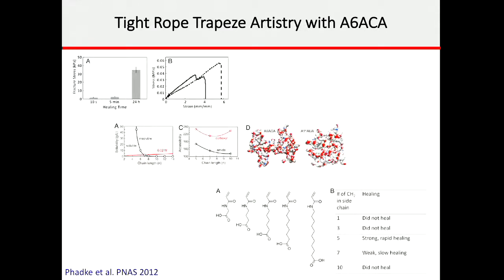Okay? Now, this paper also told us that if you have too long a chain, it folds onto itself, so as to say. If you have too short a chain, it is not able to search out. So there is an optimum balance and interleaving. That is what we saw by the molecular dynamic simulation. So this acrylyl 6-aminocaproic acid came as a result, first of an organized research to find out what the theoretical interpretation of this is, then the accidental breakthroughs that we had, then a systematic study, so as to say, and then we arrived at this decision.